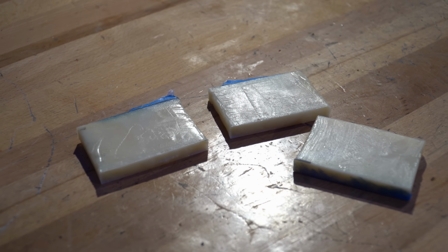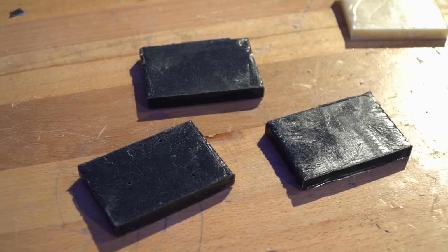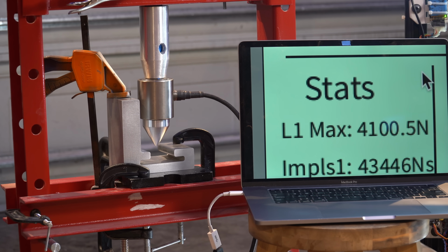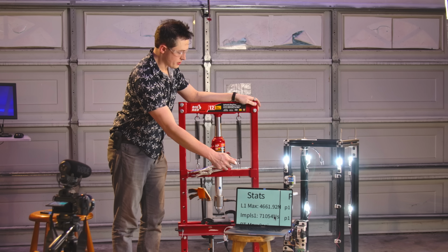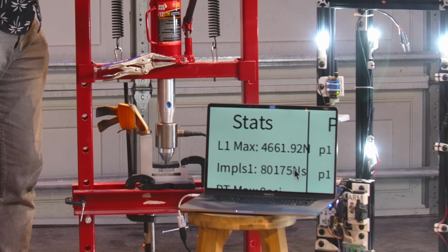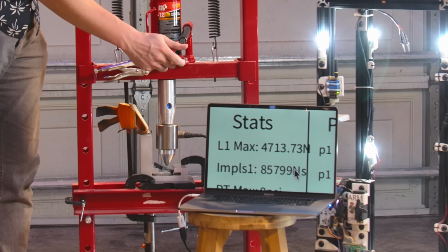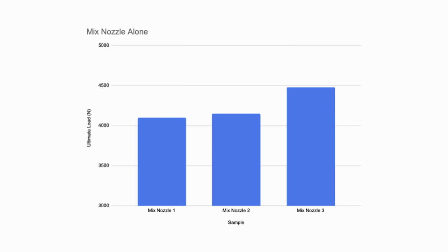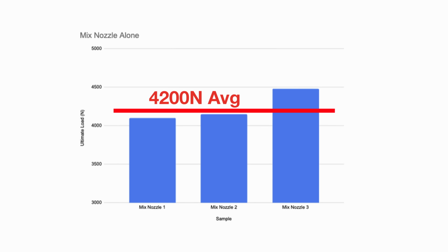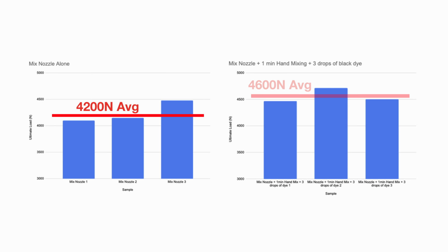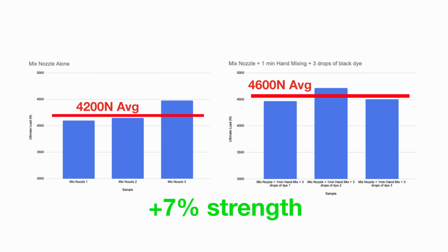Each sample was broken in the middle by a point load, a piece of aluminum that I turned on the lathe. There we go, so 4,100 newtons on test sample 1. The ultimate strength for all of them was above 4,000 newtons. The average of the 3 mix nozzle samples was around 4,200 newtons, and the average of the hand mixing samples was around 4,600, about 7% better.